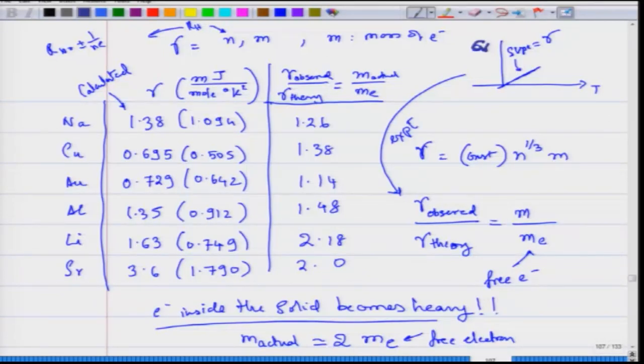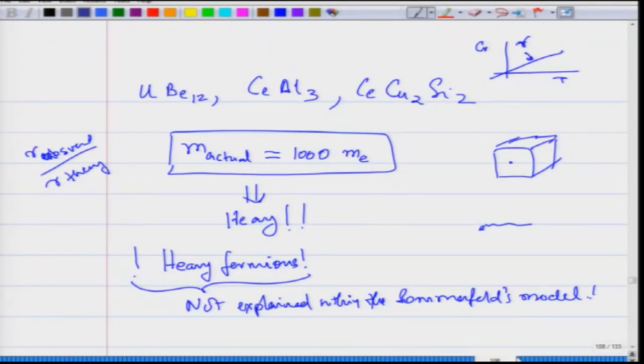And what they found is that for a lot of simple metals, the ratio is of the order of 1, namely the mass of the electron is equal to the mass of the free electron. But there are materials, as I said, where the mass can start becoming larger. In fact, as I have told you, there are heavy fermion materials in which the actual mass of the electron can be 1000 times the mass of the free electron. So these were some surprises which came up, and they pointed to limitations of Sommerfeld's model, specifically in the context of a substantial increase in the mass of the electron, which is that we have not considered